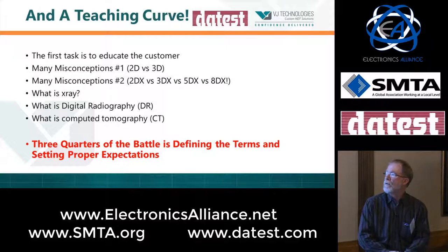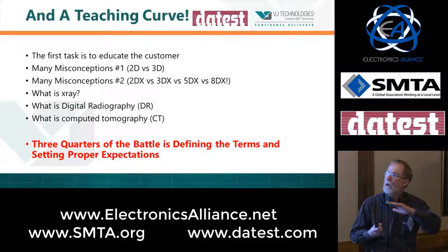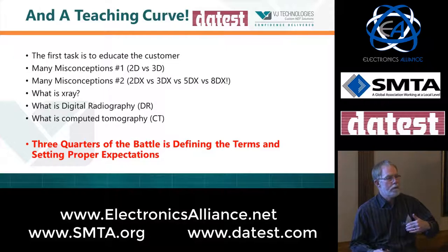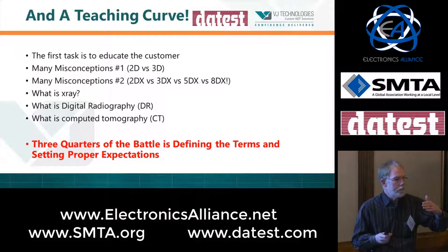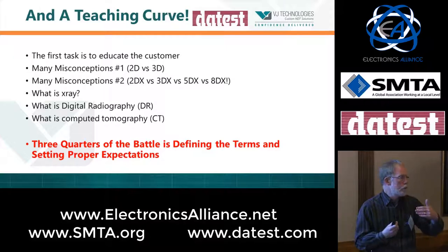What is digital radiography? Digital radiography is simply x-ray. Single shot, planar x-ray. Taking a three-dimensional object and compressing it or collapsing it down to two dimensions. Computed tomography takes that one step further and takes a series of radiographs, usually made as an object is being rotated, and then compiles those radiographs into a three-dimensional model for analysis, evaluation, failure detection, and so forth.